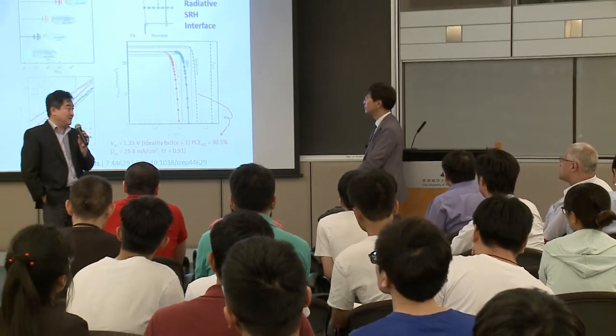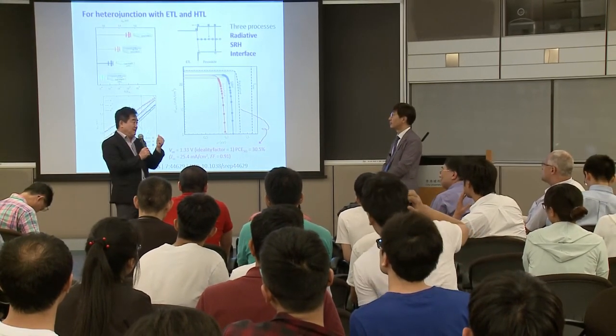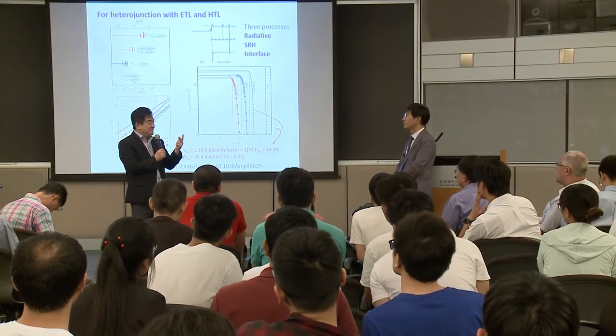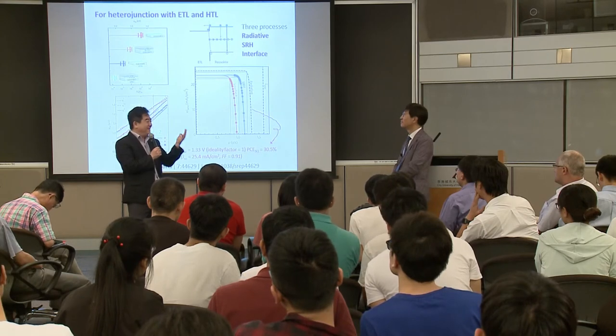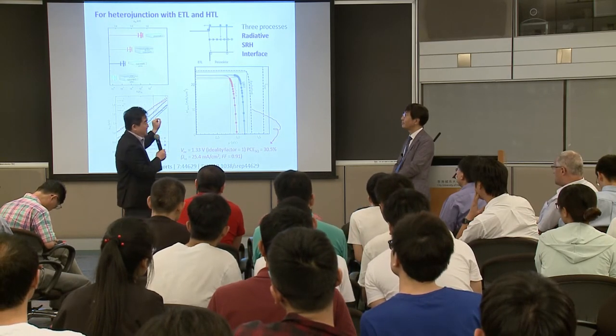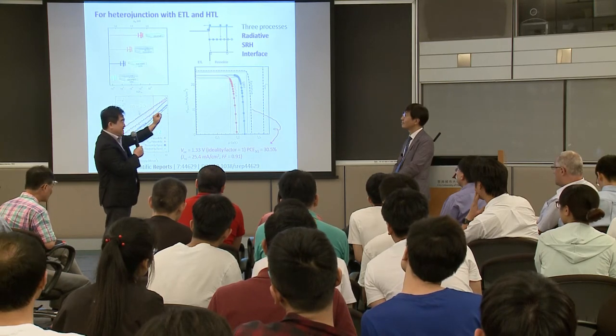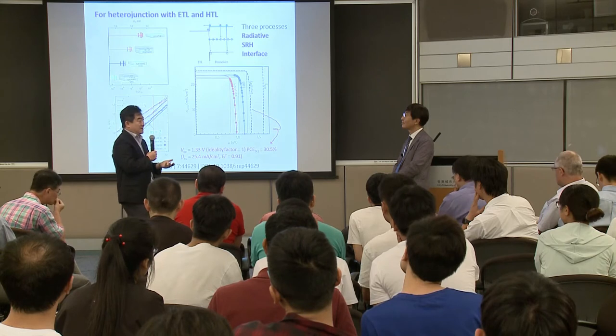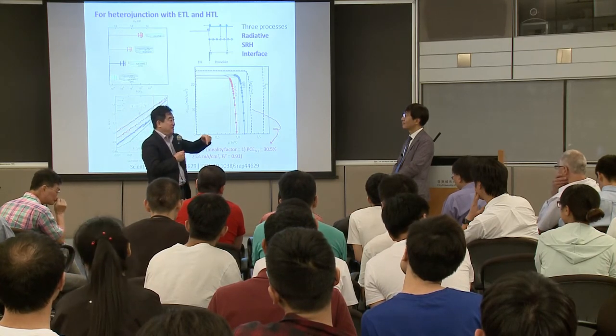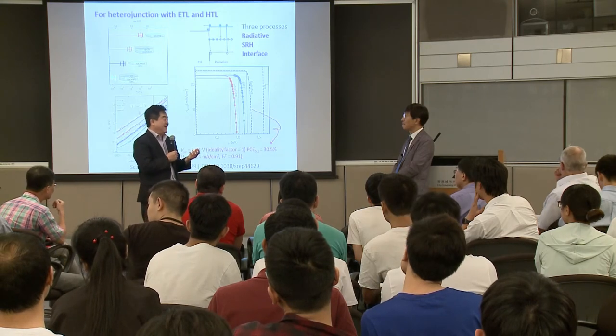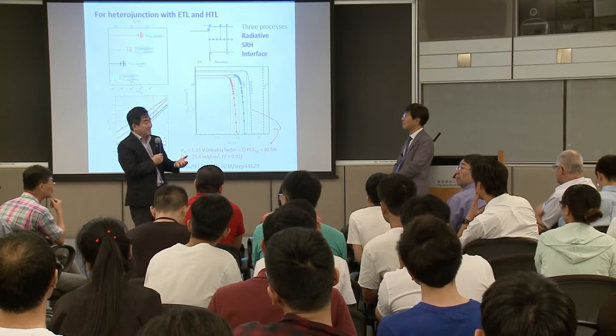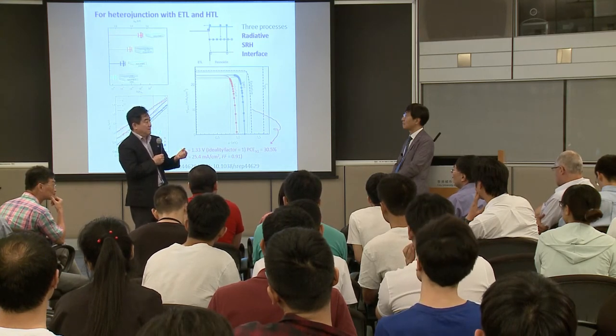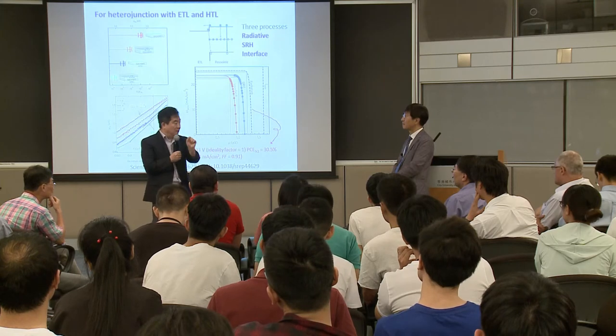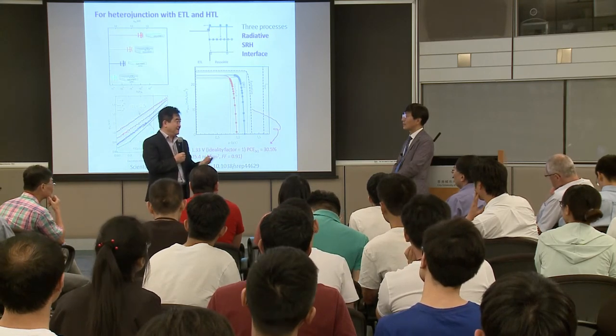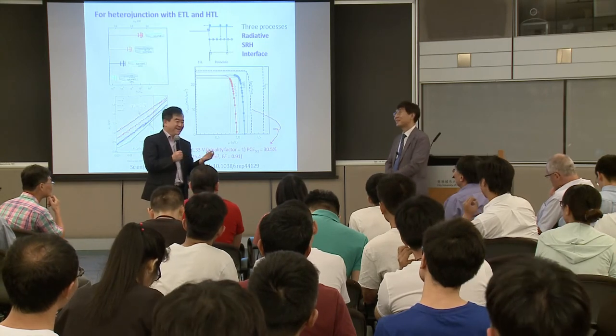When you consider all those multi-cation, multi-anion systems, you have now MA, formamidinium, cesium, then you have iodide, bromide, so five different species in there. But then when you write it, you say 0.45, 0.16, and so on. I think mostly that is based on your starting formulation, because you really cannot identify what the final product is, or the exact composition, how accurate each component in there is. So, can you comment on this?